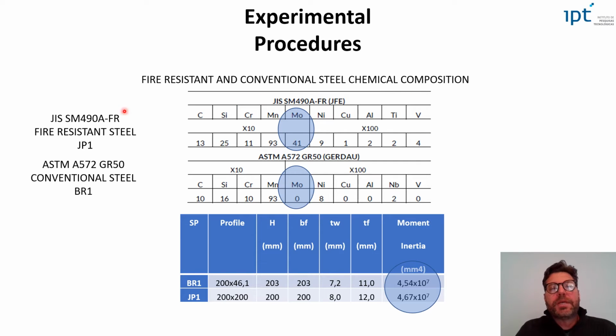The fire-resistant steel beams were produced in Japan according to the JIS SM490A-FR Japanese standard, here named JP1, and the conventional steel was produced in Brazil according to the ASTM A572 grade 50 North American standard, here named BR1. What is important to tell here is that the most important difference in terms of chemical composition between those two steels was the massive presence of molybdenum in the fire-resistant steel.